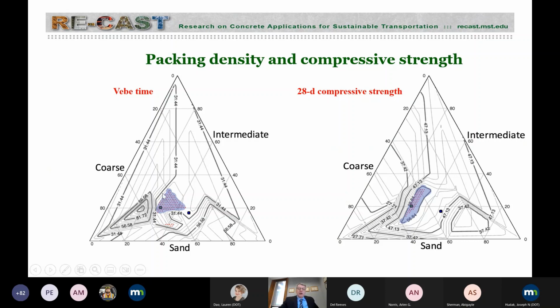The packing density that we saw earlier, this zone over here was the highest packing density, corresponds to a zone where the compressive strength was the highest. So samples that were molded and consolidated and subjected to 28 days of moist curing attained higher compressive strengths in the zones that were also the highest packing density and the lowest Vebe time. So easier to consolidate, higher density, higher strengths. And you could see with the same water cement ratio, same binder contents, just changing the aggregate distribution and combinations, we can have strengths that are as high as 57, which is about 9,000 PSI, and as low as, in this case, 27, which is about 4,500 PSI.